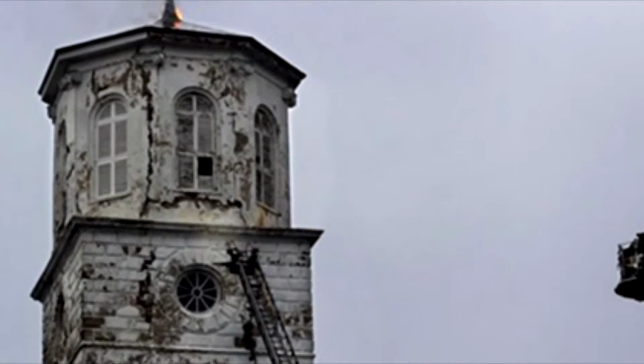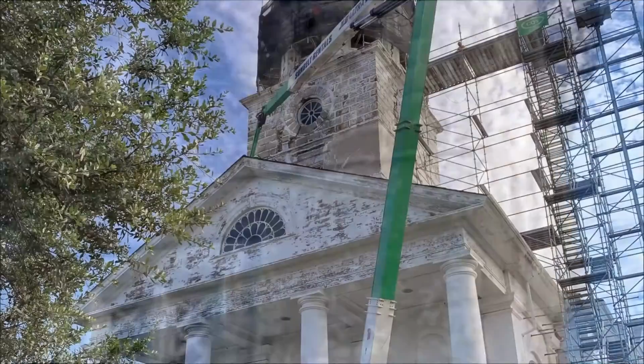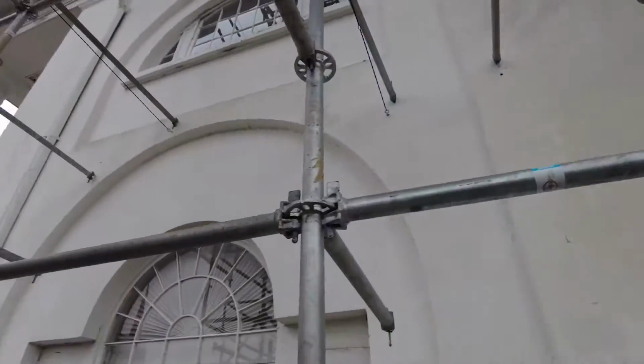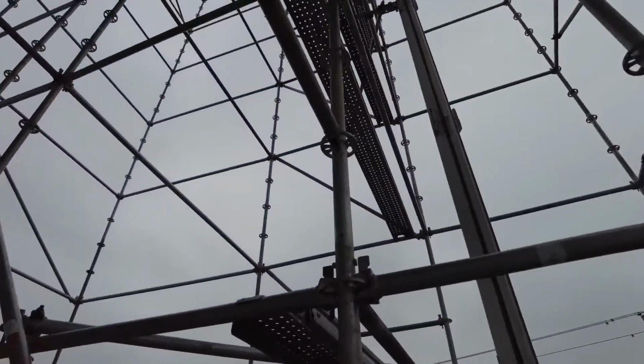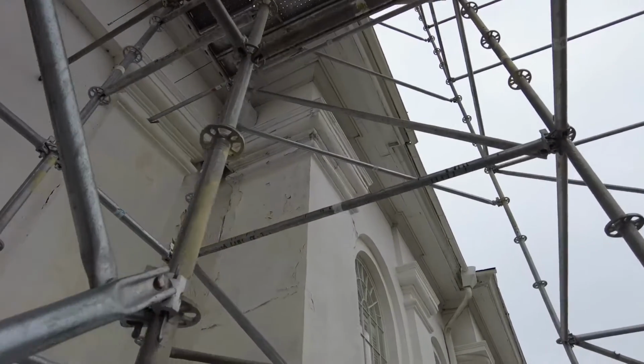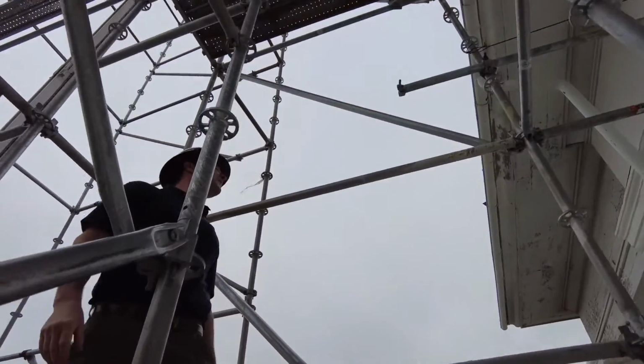So, the cracking. All that cracking probably occurred over the years since fire damage was repaired in 1960. At that time, and for years since, elastomeric paint has been used. Not only in 1960, but was again used during repairs after Hurricane Hugo in 1989. Elastomeric paint is a strong, long-lasting, watertight coating. The benefits of the paint, in theory, are great. In our situation, it ended up creating a setting well-suited to rust metal.